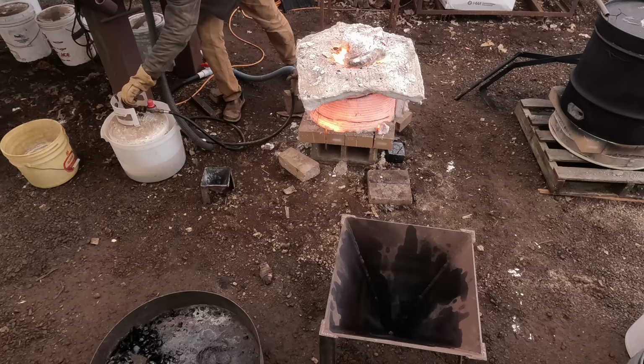I'm really excited about that first one. I got a little bit of bismuth metal at the bottom there, maybe 50 or 100 grams. If I can get 2 or 3 additional grams of gold out of each one of these, I mean, that would make it worth it. If I could get 5 grams today and 5 grams tomorrow of gold, that would be well within what's reasonable cost-wise for recovering this gold and silver. So I'm excited to see what I can get out of the metal, but let's keep going and get the rest of the slag processed.